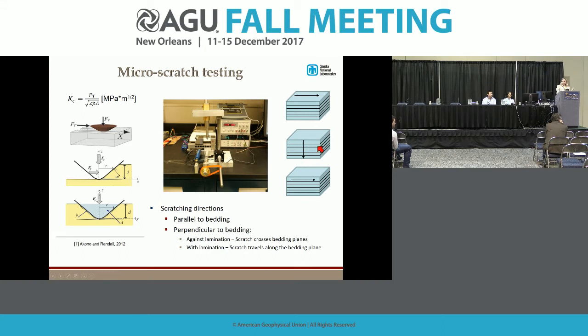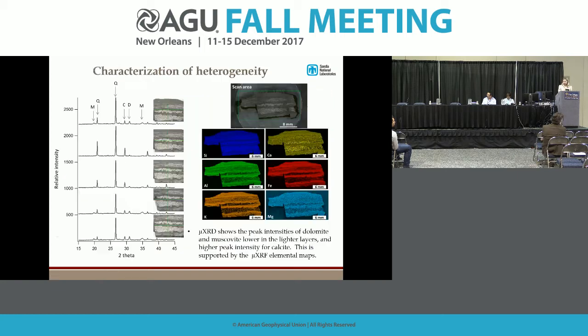With this type of scratch, we can actually see the difference in the damage between different layers, but they're really hard to quantify. So what we ended up doing, and the results I'll be showing, are applying scratching along the bedding plane in this direction. So we can actually probe individual lamina, because the resolution of our method is sub-millimeter, and the layering is within a millimeter. So it's a really good match.